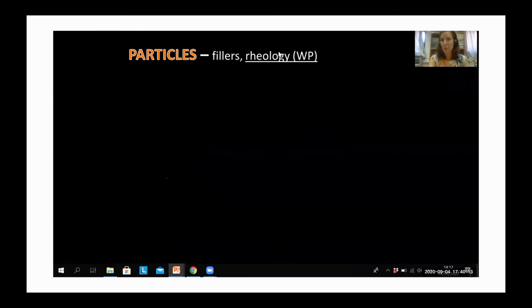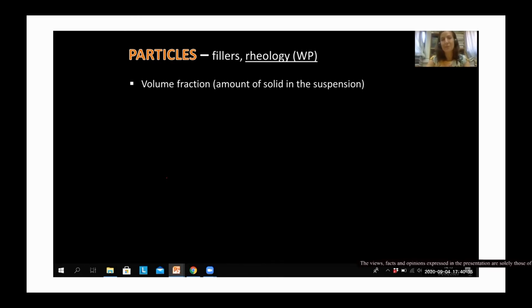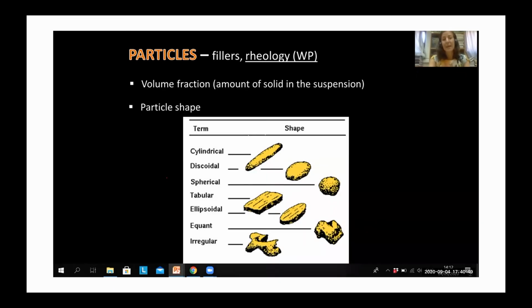So what about rheology? So working properties, when I inject my grout and it's still in the fluid state. Thinking about particles, and therefore aggregate in particular, more than binder in this case, I have different variables I can adjust. One of them for sure, and the main one I would say, is the volume fraction. It means the amount of solid I have in the suspension, how many aggregates I put, what the amount of them is, because that will hugely change things. Another very important factor is the particle shape. As you can imagine, I can have very round spherical particles, I can have irregular ones, and that will definitely change the behavior of my material in the liquid state, my rheology.